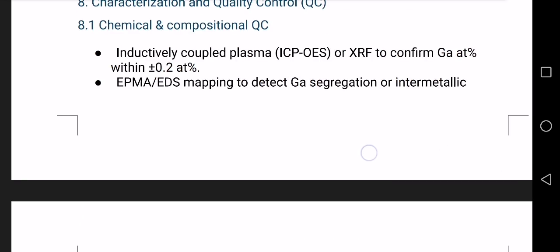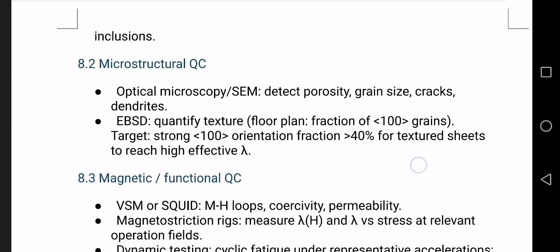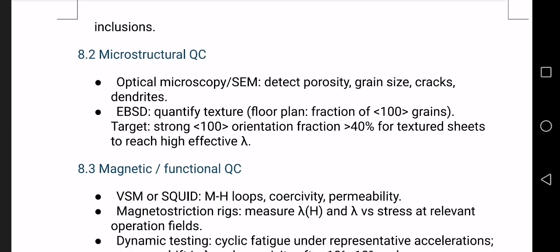Elemental mapping methods are EPMA and EDS. They are used to detect gallium segregation, find intermetallic inclusions. Now we have microstructural quality control. Microscopy is done using optical microscopy and SEM, and these are done to detect porosity, cracks, grain size, dendritic structures.